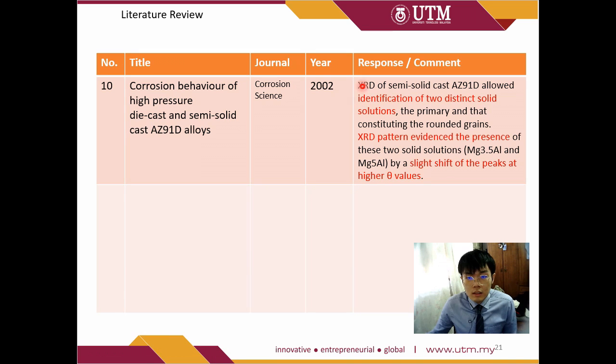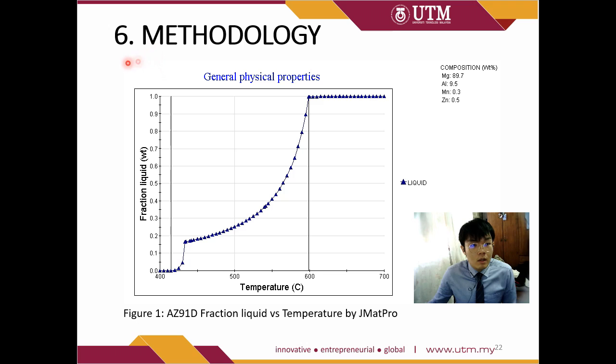And XRD allowed the identification of two distinct solid solutions, the primary one and that constituting the rounded grains. And the XRD pattern evidences the presence of these two solid solutions by a slight shift of the peaks to higher theta values. And now is the methodology.